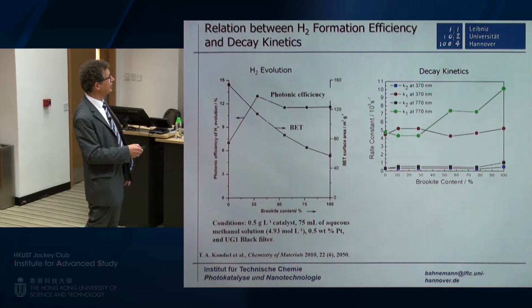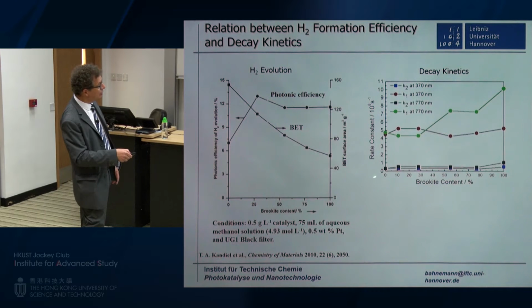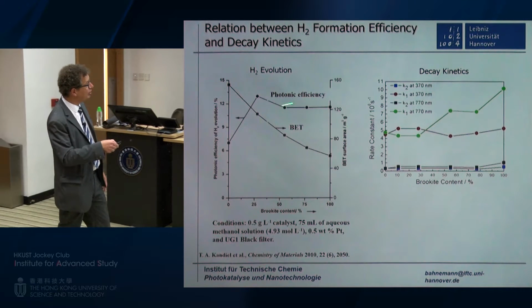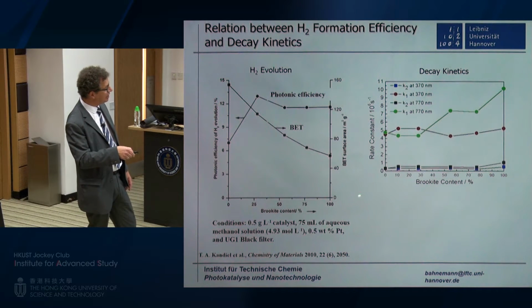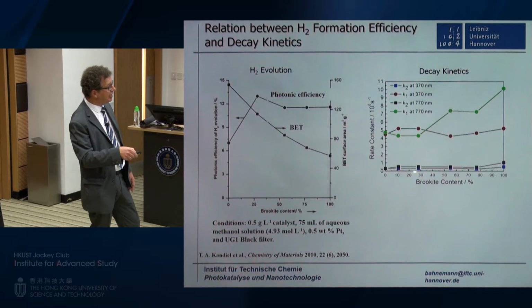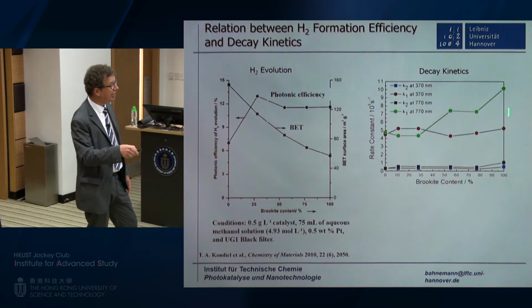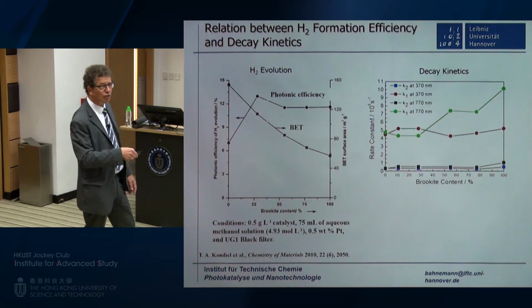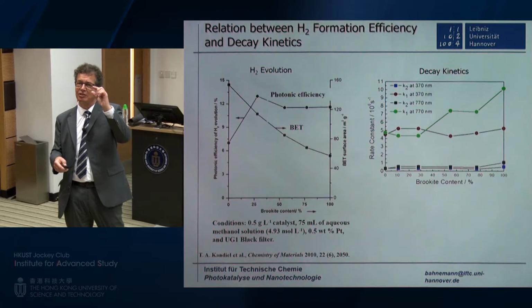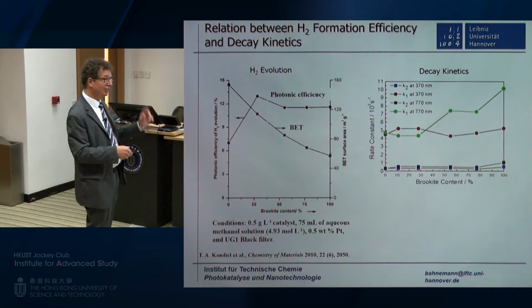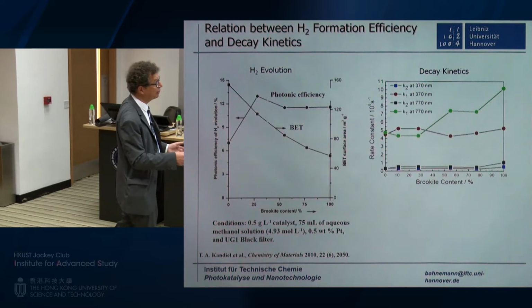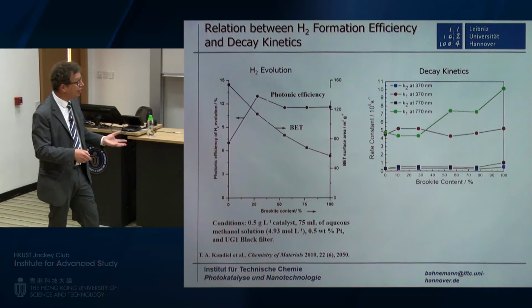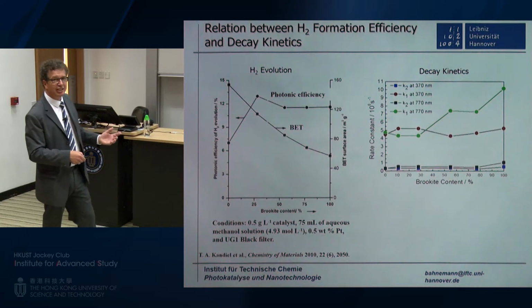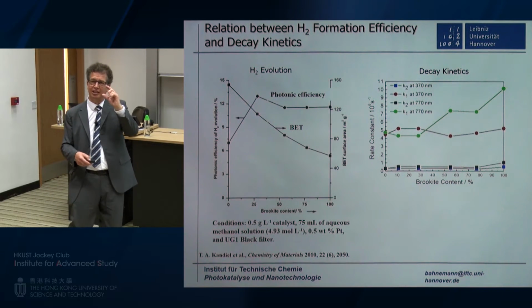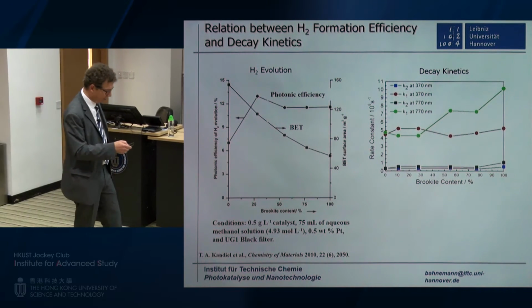And the interesting thing is, if we compare the decay kinetics at different brookite contents with the photonic efficiency, with the quantum yield of processes at these materials, you see that as the brookite content is increased, the decay kinetics are increased, and the efficiency is also increased. So faster decay kinetics means better efficiency. That is a little counterintuitive at first, because you think the longer the charge carriers live, the higher their efficiency is. But no, if they live shorter times, then they're apparently much more active in the system.